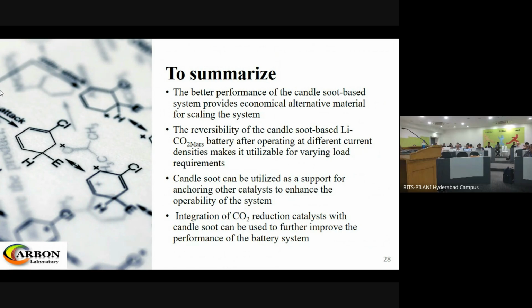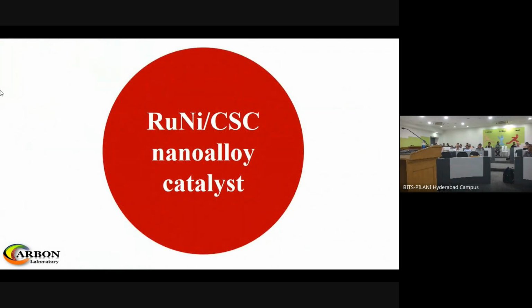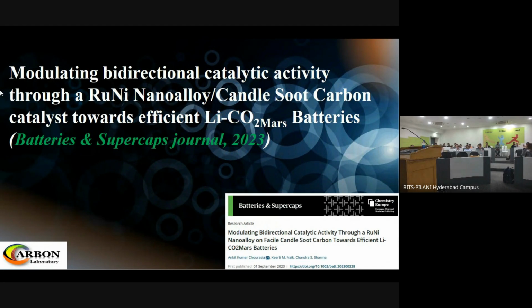And this basically leads to the next problem definition: that now the ruthenium nickel, which we have established as a better system, can we now integrate this ruthenium nickel, which is a CO2 reduction catalyst, with the candle soot to further improve the battery performance? And that is what we have done in the next work. Now the ruthenium nickel and candle soot nano alloy catalyst. This again was published last year in Batteries and Supercapacitors.